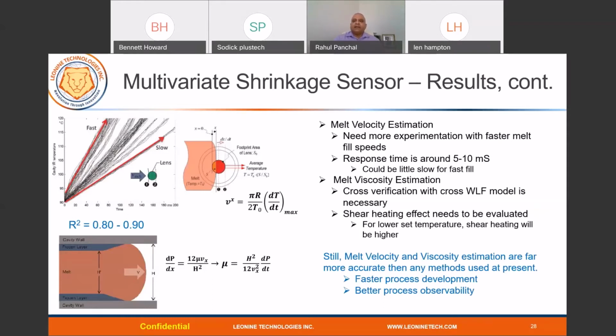It's not 95% or 99% yet, and again it needs cross verification with the Cross-WLF equation, but still it gives very good accuracy for the melt viscosity and velocity. And again, it's still very accurate compared to what people are trying to do to estimate the viscosity or velocity using thermocouple type temperature sensors or in-mold cavity pressure sensors.